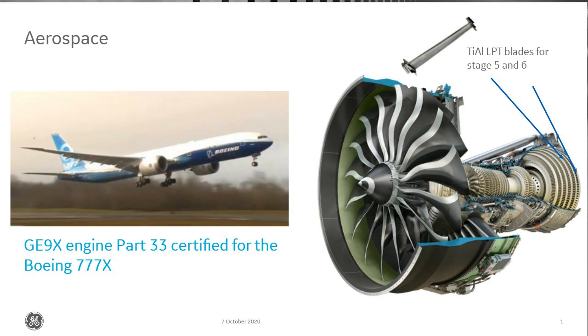As it's in the hot area, it's sometimes built with nickel alloys, but by using titanium aluminide as the alloy, you reduce the weight by 50% compared to nickel alloy, and this improves the fuel efficiency by 10%. So a lot of money to save there in fuel consumption.